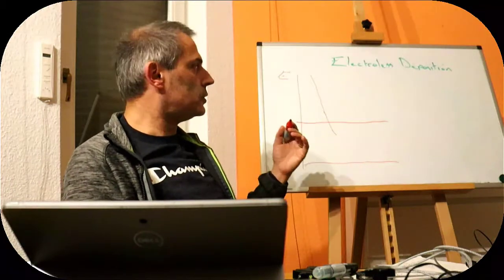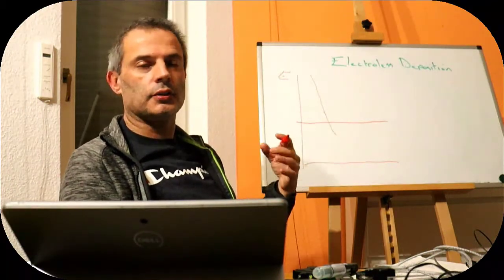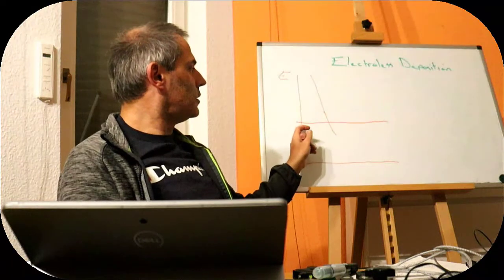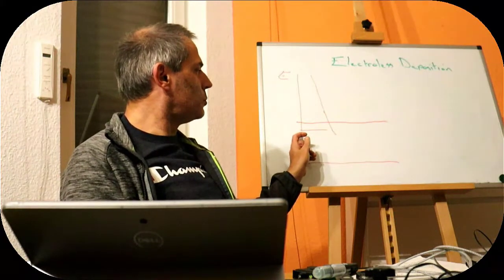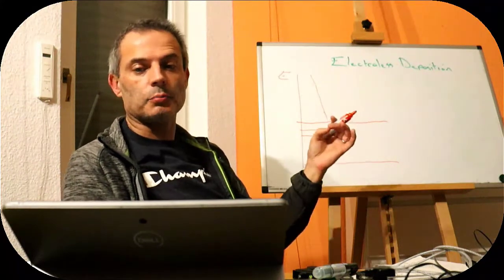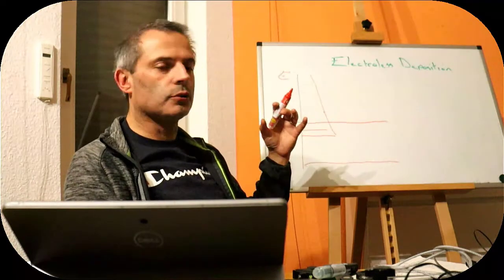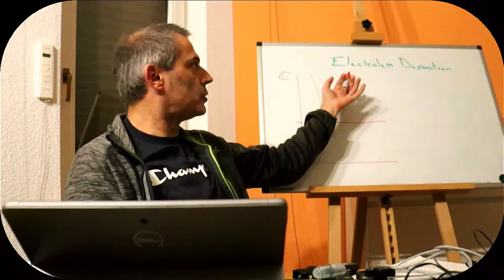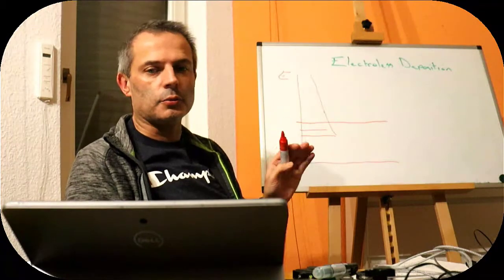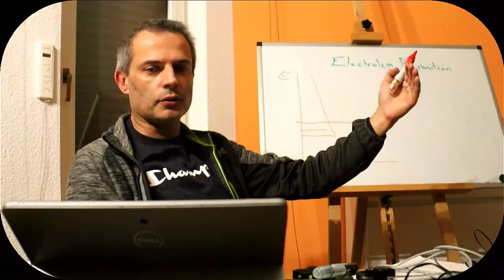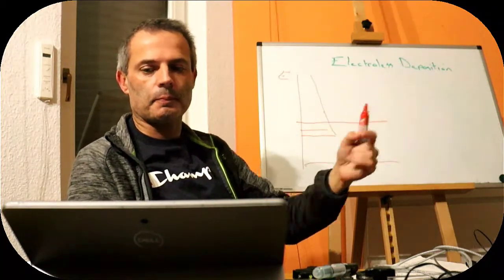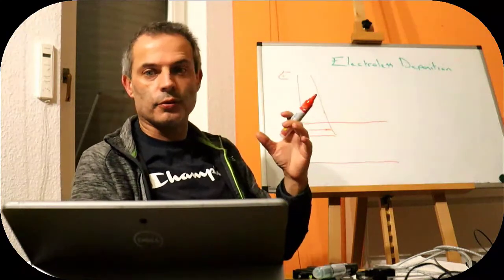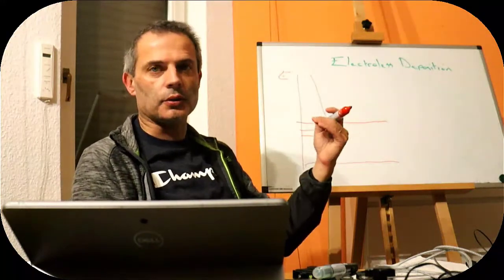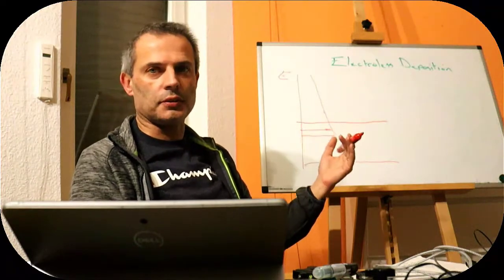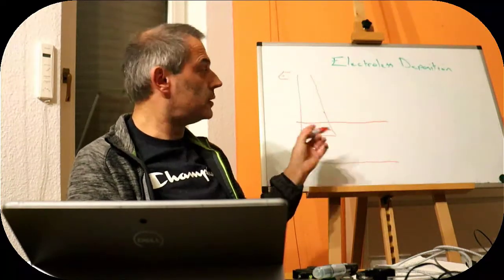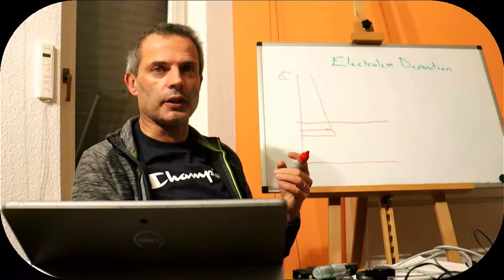So what we want in our solution is a reducing agent that is somewhere in this region but not too far down so that it makes particles on its own, because what we want for our electroless deposition bath is to put the metal onto the surface of a solid that's in there, and the driving force for it to choose to go on the solid that we want is going to be the surface energy that we would need to make new particles or to coat something else.